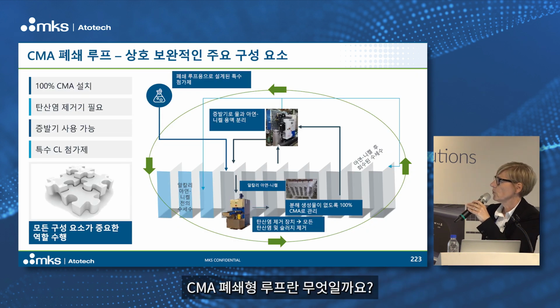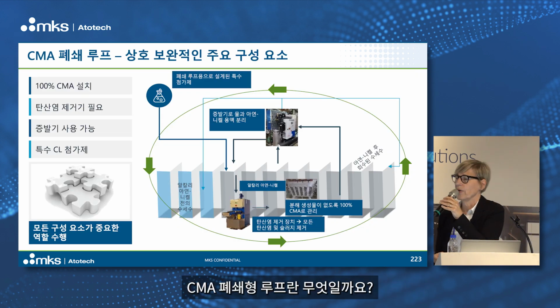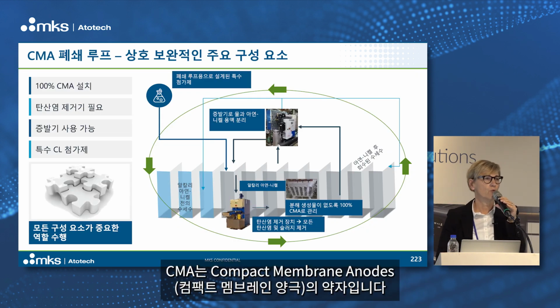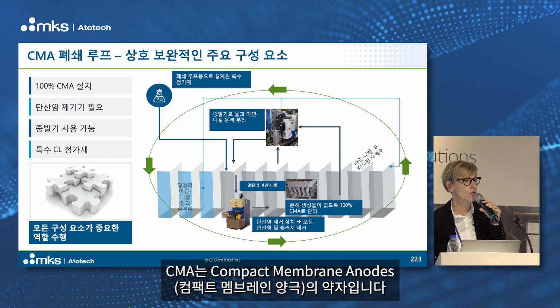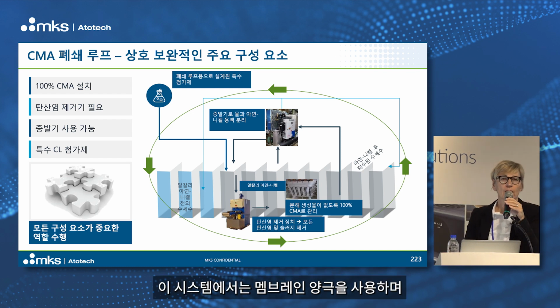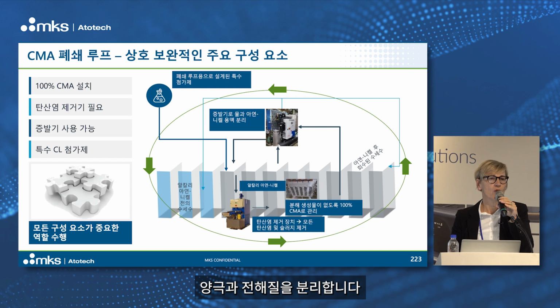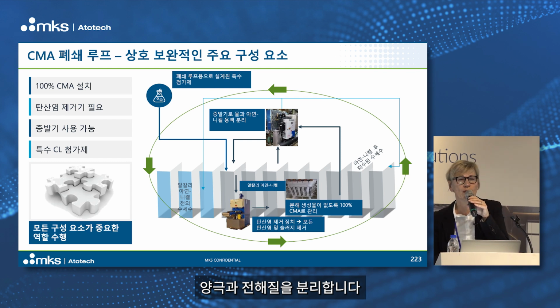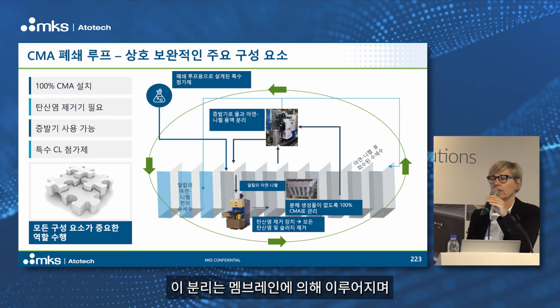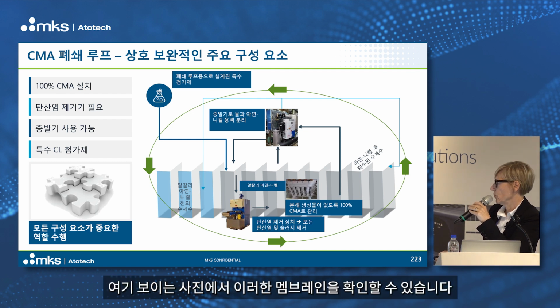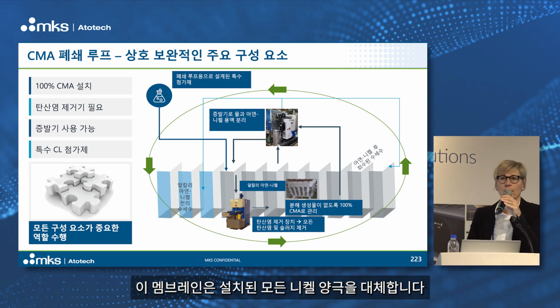Have a look at what CMA closed loop is. CMA stands for compact membrane anodes. So we are using here anodes which are separated from the electrolyte. So we are using their separation by membranes. These membranes you see here on this picture, they are replacing all the nickel anodes in the installation.